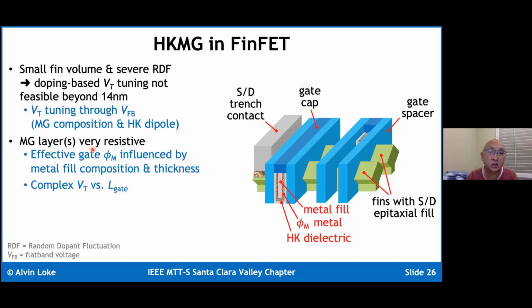What I want to mention also is that the metal gate layer, which sets the work function, which comes in intimate contact, unfortunately, nature's not very kind to us. It gives us the right work function, which allows us to set the flat band voltage and therefore the VT correctly. However, because it's very resistive, the effective work function of the gate is influenced not just by the work function of the work function metal, but also of the metal fill, that lower resistance metal fill that you have, okay? And so this gives rise to very complex threshold voltage versus gate length behaviors, okay?